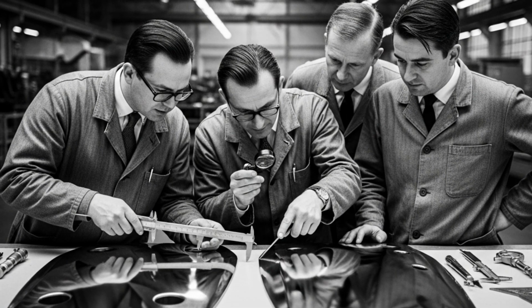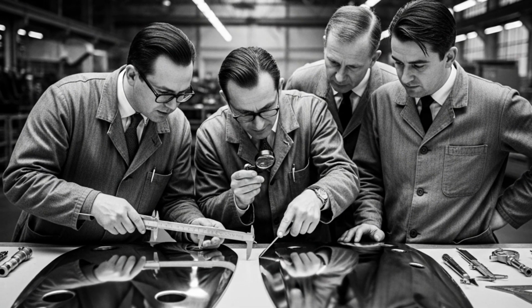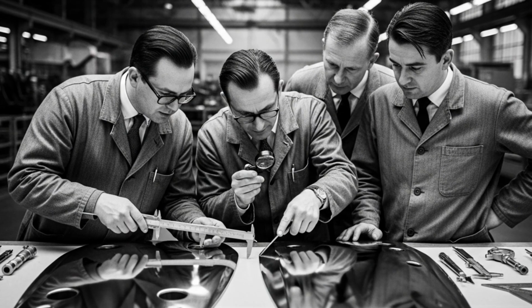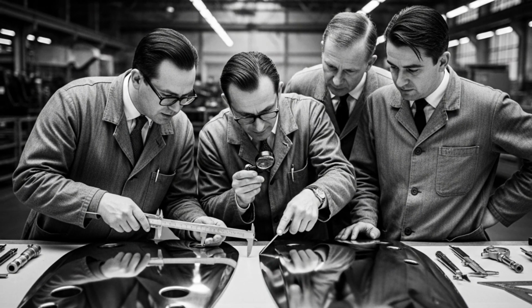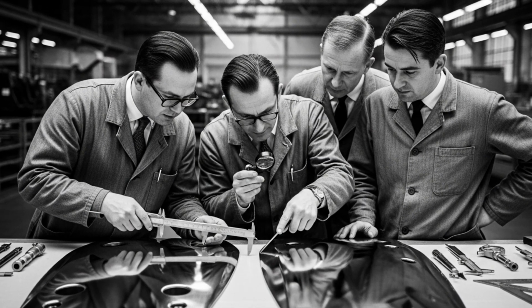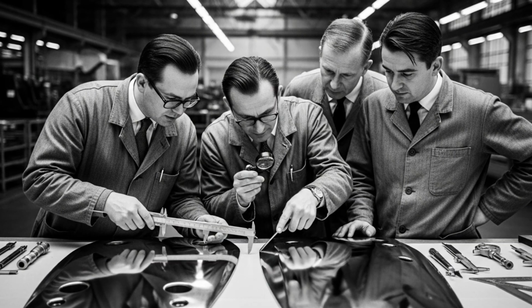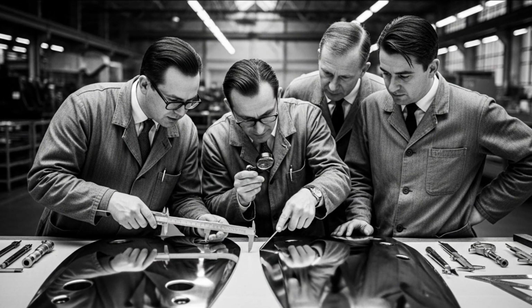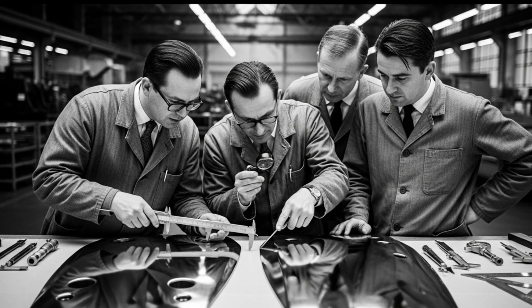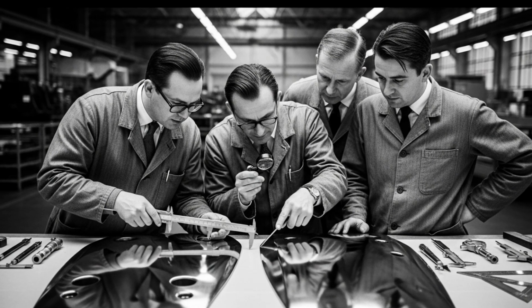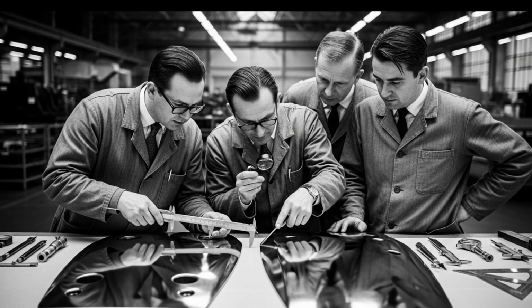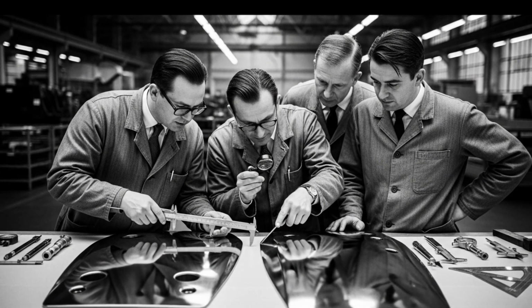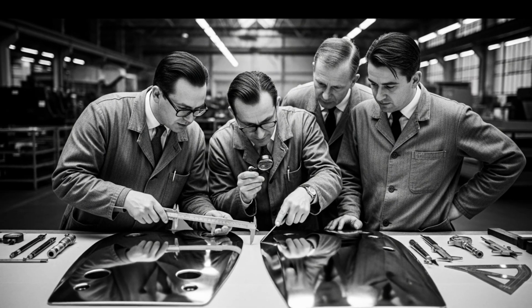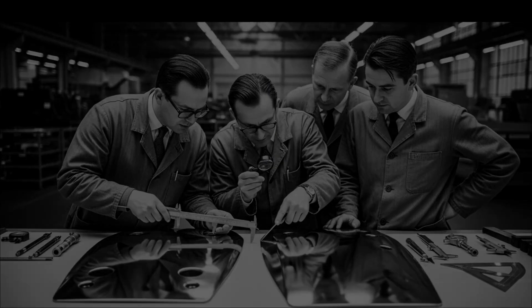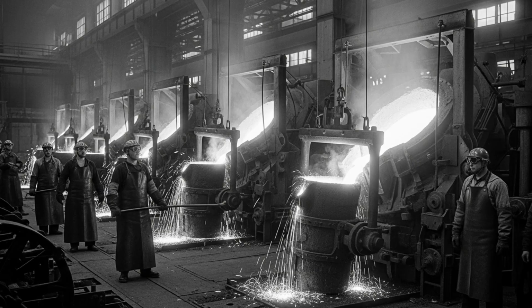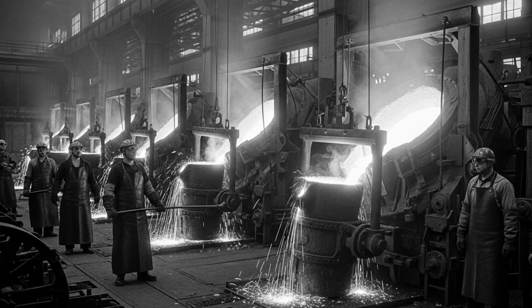The philosophy was simple. If scrap steel could not meet the standards for armor plate, then change the standards. If impurities could not be completely removed, then dilute them to acceptable levels. If the crystalline structure was inconsistent, then design around the inconsistency. The question was not whether the steel was pure, but whether it would stop a shell. And if it would stop a shell, even imperfectly, even with a higher chance of cracking, then it was good enough, because the alternative was no tank at all.